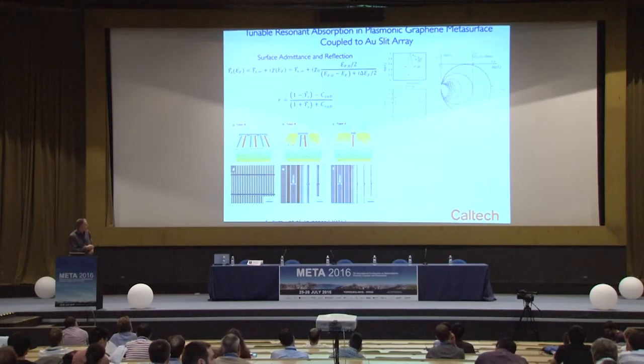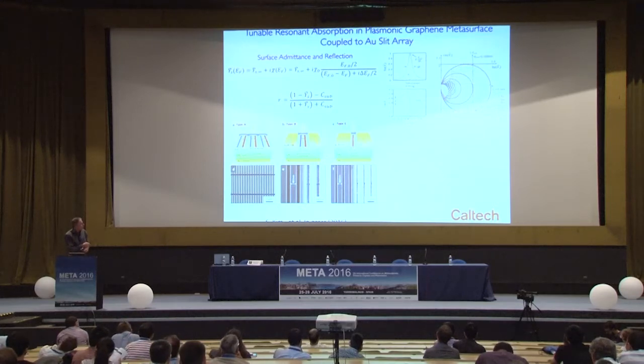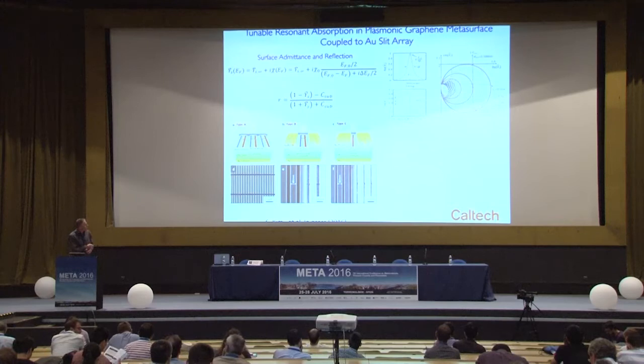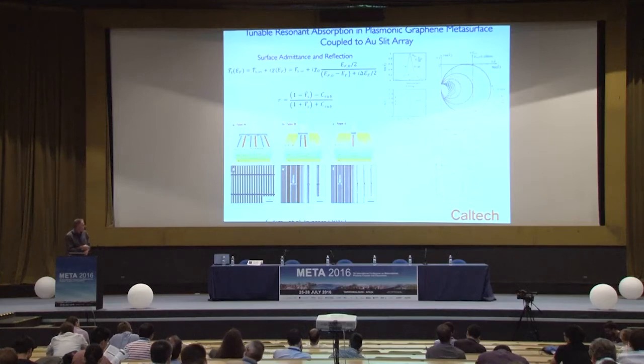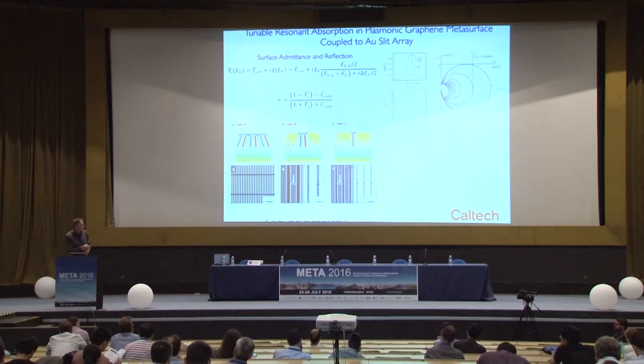And what we can see then, and the electrical engineers in the audience will recognize, is that we can use a simple Smith chart analysis in which this substrate coupling factor represents a tuning parameter for the real part of the effective admittance, and allows us to identify the condition. Essentially, there's a critical mobility in the graphene that defines the conductance and therefore the real part of the admittance. And what we're really trying to do to maximize absorption is to match the conductance and the admittance to free space. And so, for a fixed set of properties, as we change the conductance by the mobility, we find that there's a critical point here where we impedance match and expect to get to unity absorption.